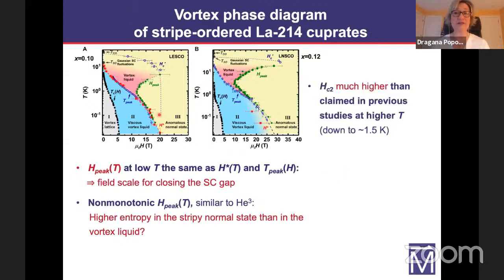Also, the upper critical field that we found here is significantly higher than what was claimed in previous studies on these same materials that have been conducted at higher temperatures. For example, in LESCO, the study was down to 1.5 Kelvin and up to lower fields. So it was concluded that the upper critical field was about 8 Tesla. So perhaps if we had limited our study to such a narrow range of parameters, we might have reached the same conclusion. But what this also shows is that it is necessary to go to temperatures that are orders of magnitude lower than the zero field Tc in order to make reliable extrapolations to zero temperature. And of course, one needs to, in transport measurements in particular, be very careful with current excitations and conduct nonlinear transport measurements.